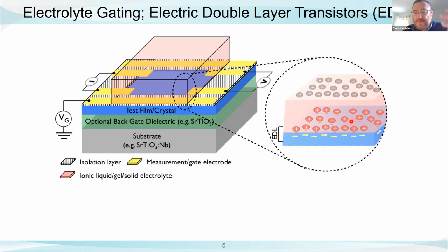Then cations will be driven down to the surface of our magnetic oxide. They won't be able to penetrate, so they'll accumulate in a sheet. And on the other side of the interface, we'll induce a controllable density of electrons. We'll electrostatically dope our material. Now, the beauty of this is that this thing that forms, which is called an electric double layer, is essentially a nanoscale parallel plate capacitor that completely decouples the thickness from the capacitance.